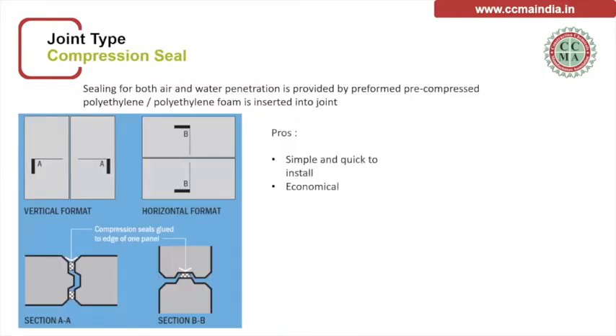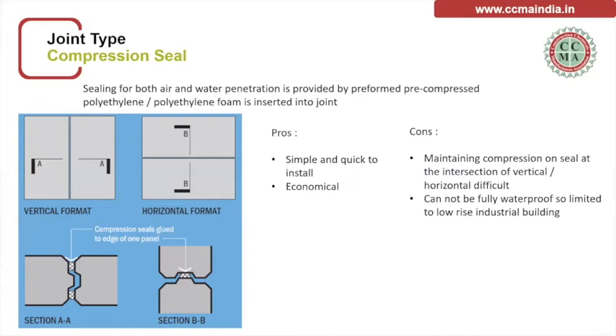Last type is the compression seal, where sealing for both air and water penetration is provided by preformed, pre-compressed polyethylene foam, which is inserted into the joint. You can see the vertical and the horizontal section. Advantages: it's simple and quick to install. It's just like providing a gasket around the panel. But drawbacks: maintaining compression on the seal at the intersection of vertical and horizontal is difficult. It cannot be fully waterproof, so it is limited to low-rise industrial buildings, because this polyethylene foam suffers from compression set and doesn't offer resiliency. So that is why it cannot be fully waterproof.